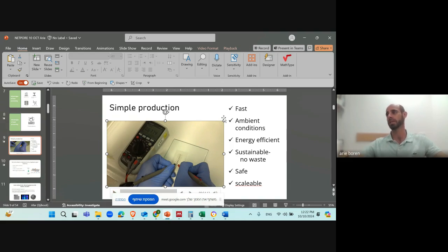And so all these advantages you've seen in the movie, it is very fast. In just seconds, you can have the graphene instead of a lot of hours. Everything is done in ambient conditions. You don't need inert atmosphere. And why is that? Because if you heat up carbon in any form more than 300, 500 degrees Celsius, it will burn off in the presence of oxygen, right?